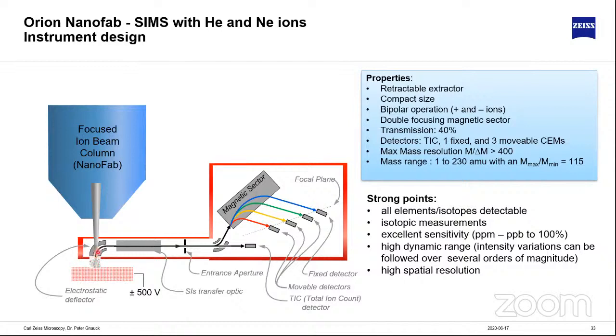Therefore, we decided on this instrument to use a magnetic sector field mass spectrometer that measures in a constant mode. It measures all the time. That means we have no duty cycle, and that means the signal that we get is a factor of 1000 higher compared to what we would get with a TOF SIMS. And in addition to that, we have a transfer optics that extracts all the ions that we generate, transfers them into the entrance aperture of our magnetic sector field, and then we can do very nice SIMS analysis here.